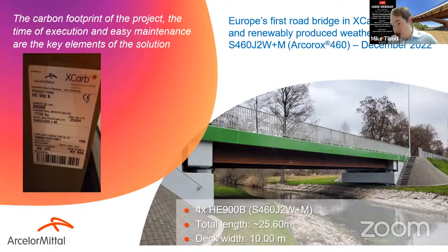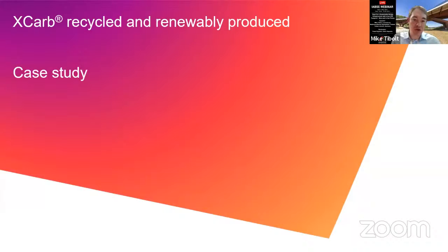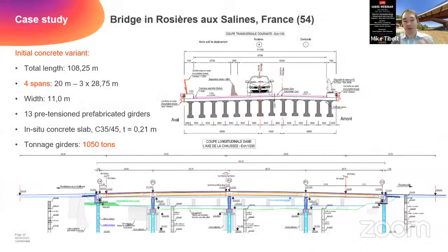And in your design, you have to reduce all the thickness of the surfaces which are in contact with the environment. And of course, in this case, you would end up normally with higher profiles. But if you combine it again with S460 steel, you can compensate for this effect. And that's why it could be very attractive to use this solution. And here I'll show you a small case study, which is in fact a bridge, Rosières-aux-Salines in France, which was initially foreseen in pre-stressed prefabricated concrete girders.